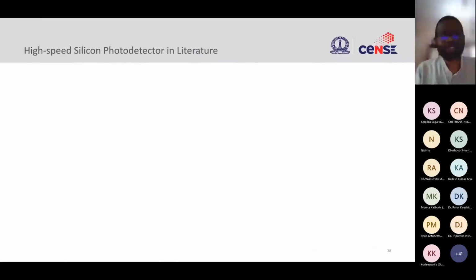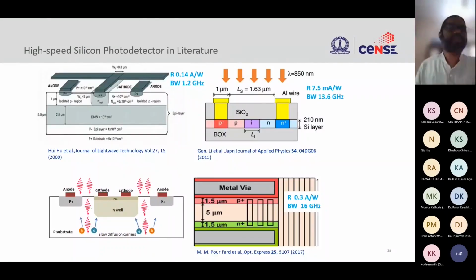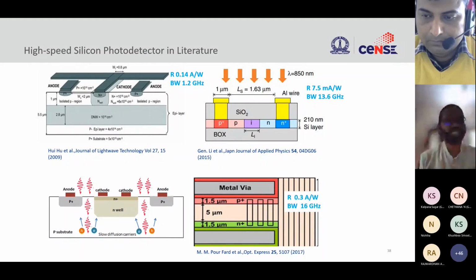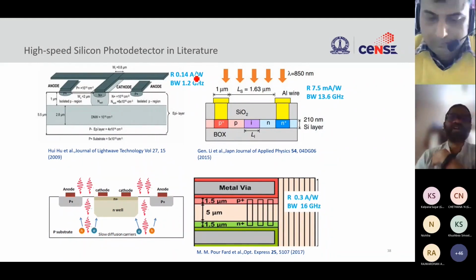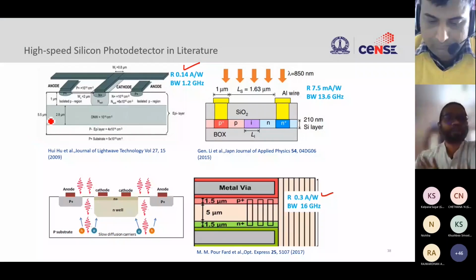And silicon is again a CMOS material that we can use. We went ahead and asked, what are the possible thin film silicon photodetectors available in literature? We looked at it, and there are various demonstrations done, but all of this without any guided wave system. So you cannot guide light. You just shine light and you measure the current, that's all. And you can see that responsivities are rather low. We are talking about 0.14 amp per watt. This is 7.5 milliamps per watt, and then it is 0.3 amp per watt. This used to be the highest before our demonstration. I will show you what we were able to demonstrate. But these are all thin film detectors.